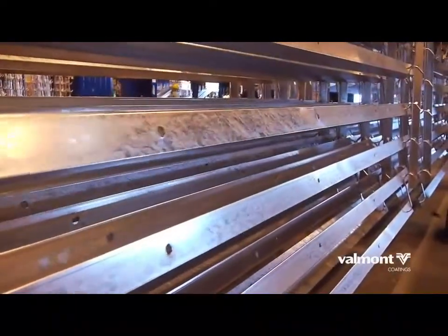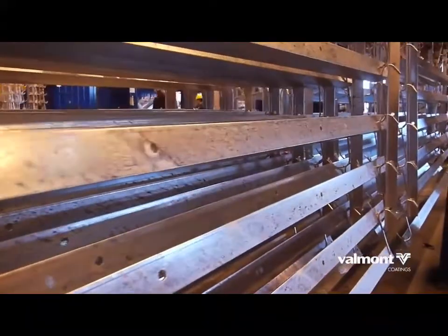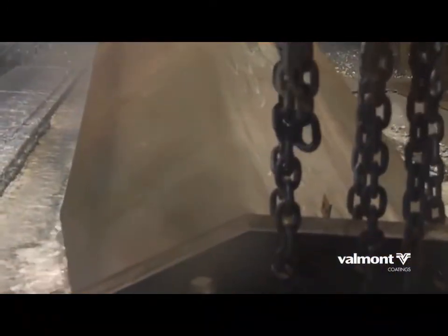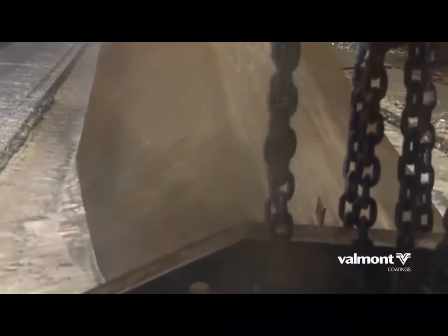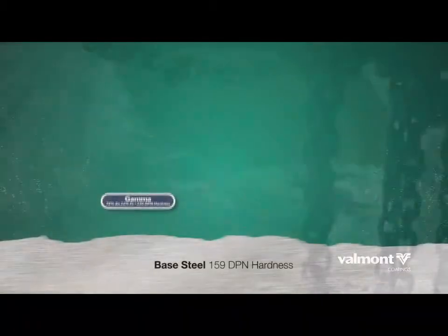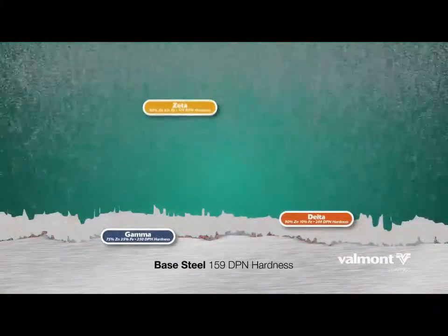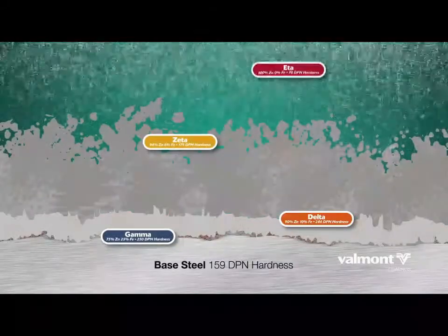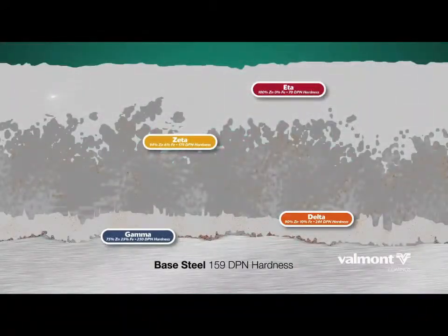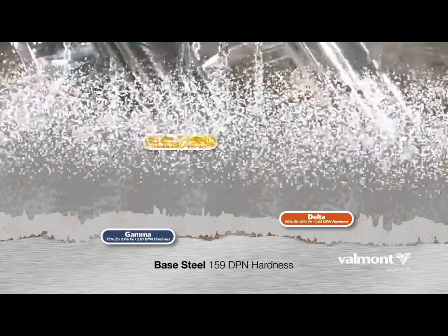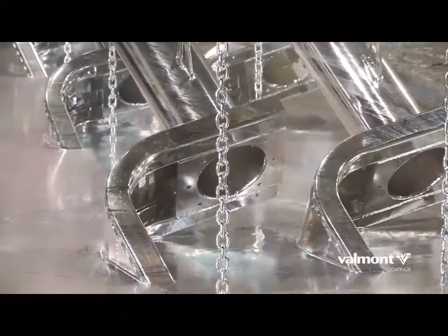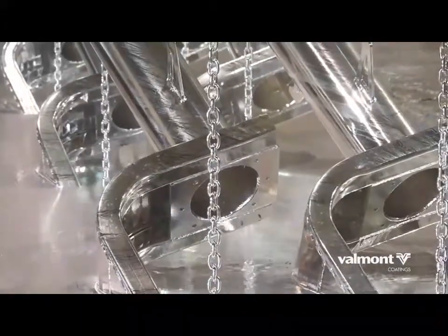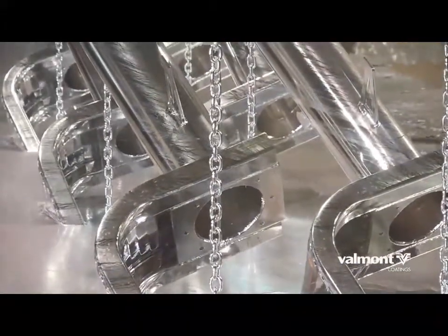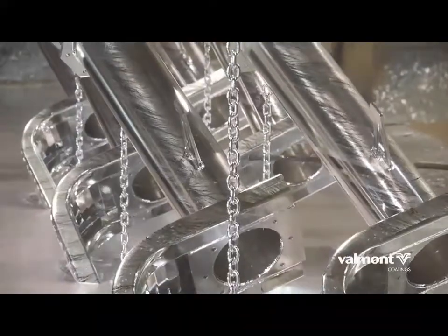And when combined with steel, there is a 70% recycled content rate, which easily meets LEED credit requirements. In the field of metallurgy, zinc has a special relationship with steel. In the bonding process called hot dip galvanizing, the zinc chemically bonds with the steel to form a series of zinc-iron alloy layers. The final layer is 100% zinc. These tightly adhered layers become extremely abrasion resistant because the intermetallic layers are harder than the base steel. So the protective zinc coating actually becomes harder than and part of the steel used in the structure.